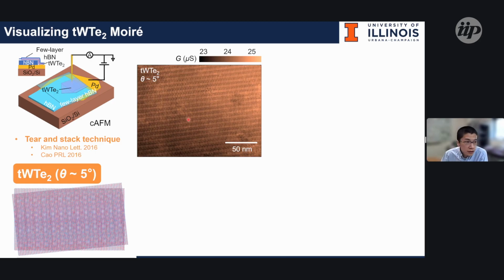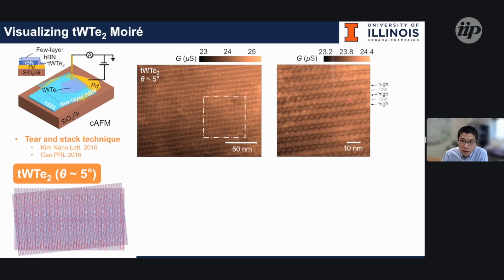You can see here the interchanging of the 1D structure, and even compute the distance between the wires. If you compute here, this is a 5-degree twisting. The measurement in the conductive AFM image is around 7.1 nanometers, which is very close to the theoretical computation of around 7.2 nanometers. This shows us that there is almost no lattice reconstruction in such a system.